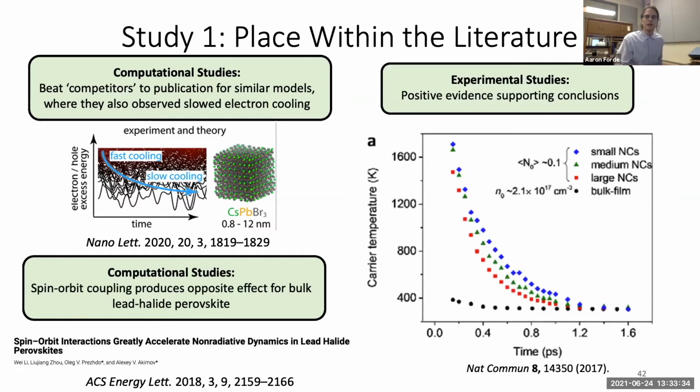From the experimental study that I mentioned earlier, where they measure carrier cooling dynamics for various systems, going from red to blue goes from large to small nanocrystals. And in their experiments, the smaller nanocrystals showed much longer decay times, and even seem to slow down closer to the band edge. Whereas for the bulk, the carrier cooling happened much quicker than the resolution time could even allow. So it seems that these results give a good overlook of the non-radiative processes in these lead halide perovskite materials.